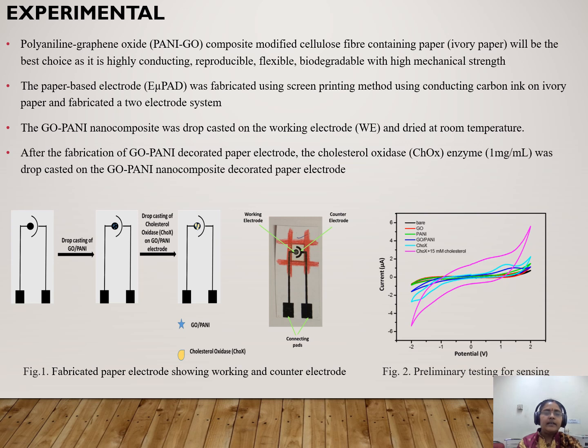Once the polyaniline graphene oxide was drop casted, the next step is to immobilize the enzyme. The cholesterol oxidase, 1 milligram per ml, was taken and drop casted on top of this graphene oxide and polyaniline composite. As the graphene oxide and polyaniline composite has many functional groups, no mediator is required to immobilize the enzyme on the electrode.